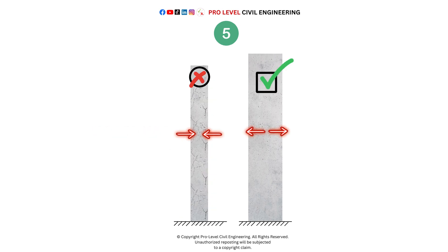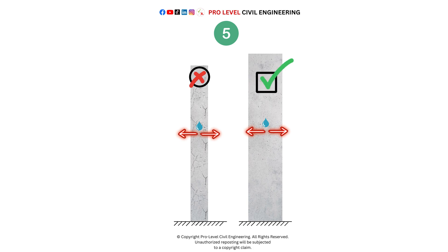5. Increasing the cross-sectional area of members — large concrete members have a high volume relative to their surface area, meaning there is a lot of material in the center that is far from the surface. In these large members, creep is proportionately less because the free water inside the concrete takes longer to escape to the surface. As a result, the process of deformation due to creep happens more slowly and less intensely.